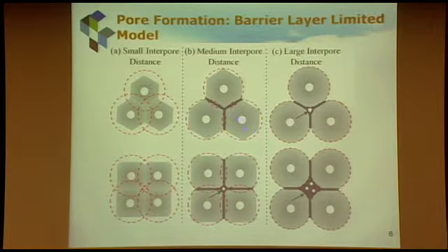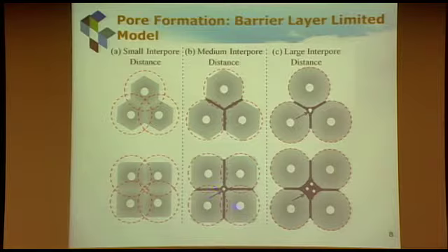But if you're at the right pore distance, these boundaries just overlap, and you start seeing that cell-like structure. And when they are further apart, you have this possibility of creating a new pore. However, for the square arrangement, you're not looking at this direct distance, you're looking at the diagonal